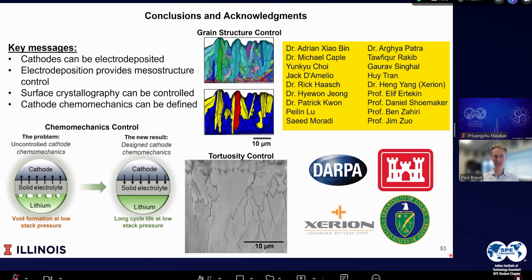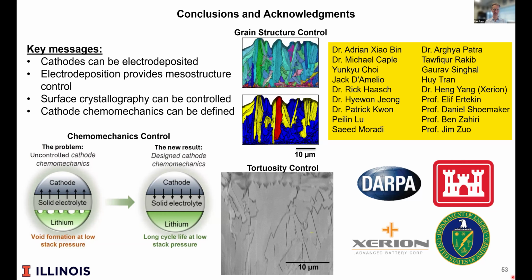Yeah, that's a great question. We've developed processing phase diagrams. What we did is we explored the effect of precursor concentration, electrolyte chemistry, temperature, and current density. From this, we can find regions where the material predominantly grows with the vertical orientation, and other regions where it predominantly grows with the horizontal. Usually the vertical orientation grows under higher current density and lower temperature, and the horizontal is closer to what we would call thermodynamic control. In those systems, it tends to grow with the layers near parallel to the surface.